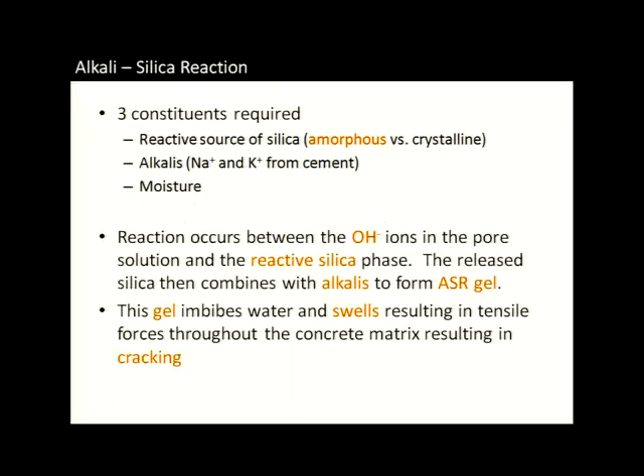So I'm going to spend a lot of the rest of the talk discussing alkali silica reaction. So we're going to discuss one of these main degradation mechanisms that can limit the long-term performance of concrete. Don't worry, we're not going to get into too much chemistry. This is the only slide you're going to see on a little bit of chemistry. But the idea here for alkali silica reaction is that everything we put into concrete initially can actually set up the parameters to have this form of attack somewhere down the line. So you see that you need three constituents. You need a source of reactive silica, and that's coming from the aggregates.